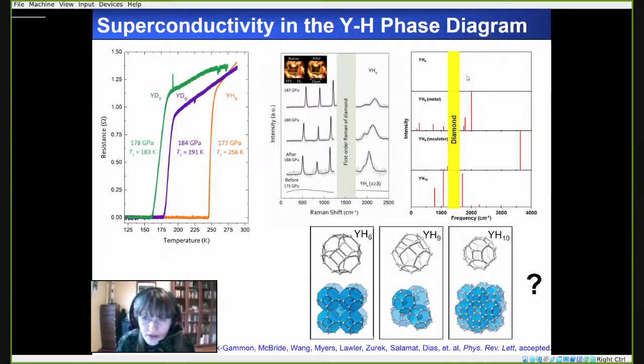And if we obscure that region from our calculated results, we see that the structure cannot be YH6 because it would not have any Raman visible peaks. There is a YH9 insulating phase that was also predicted by theory. It also does not have any peaks within the frequency region that Raman observed. It does, however, have a very high frequency peak. So this cannot be the structure that was synthesized.